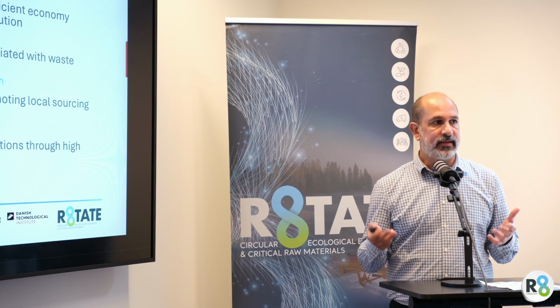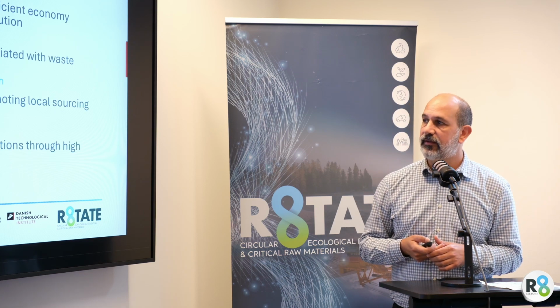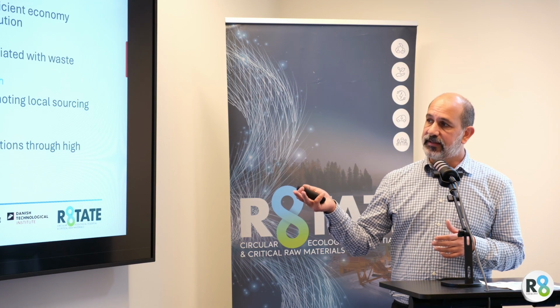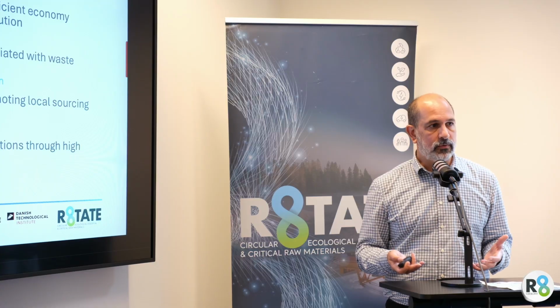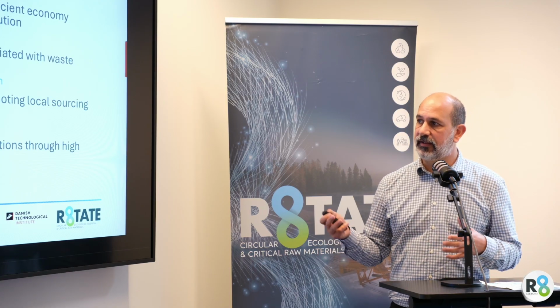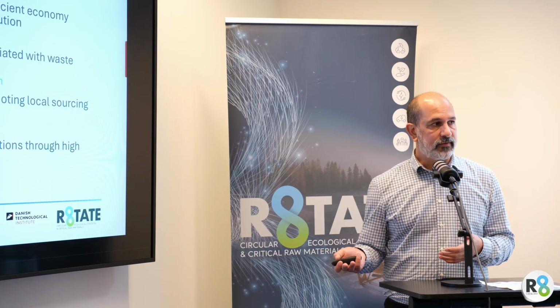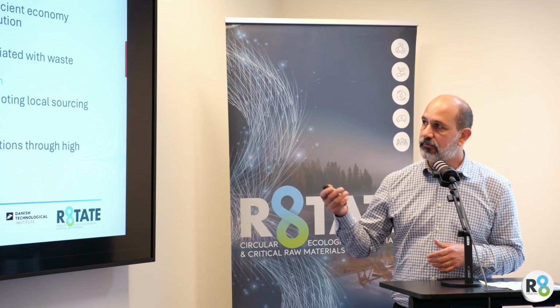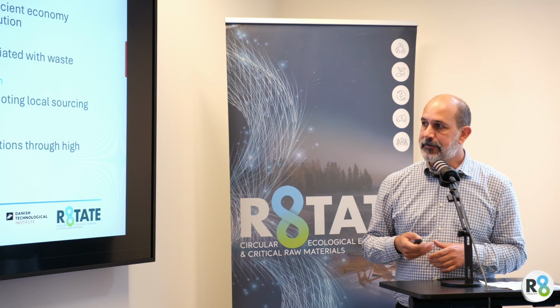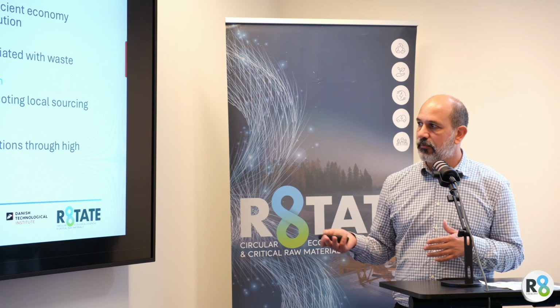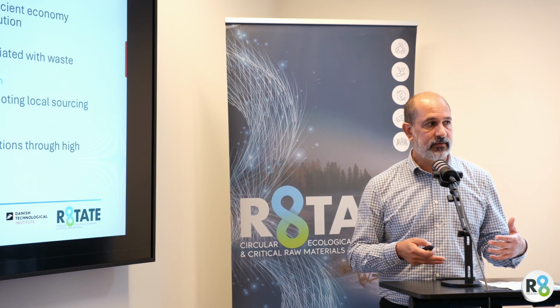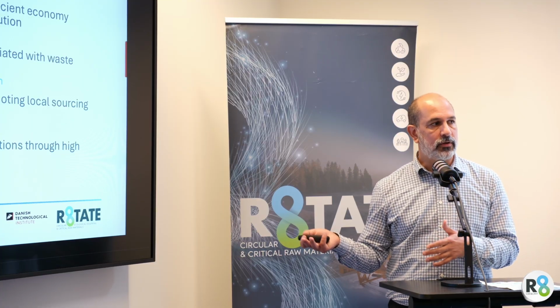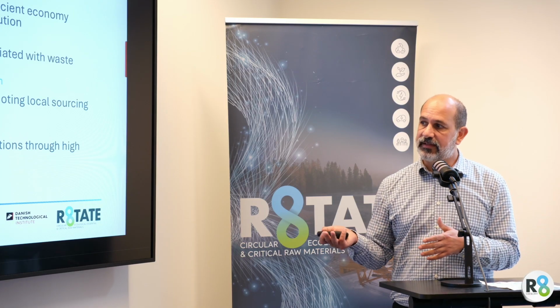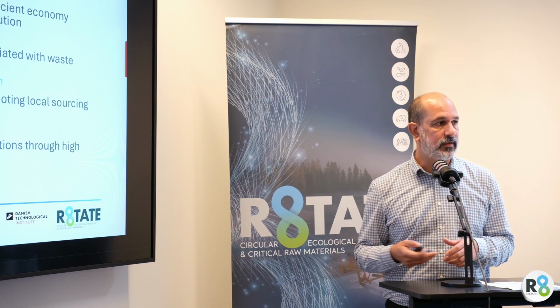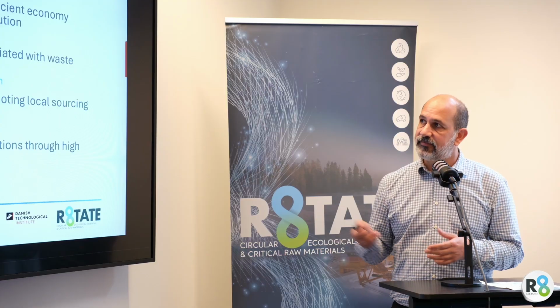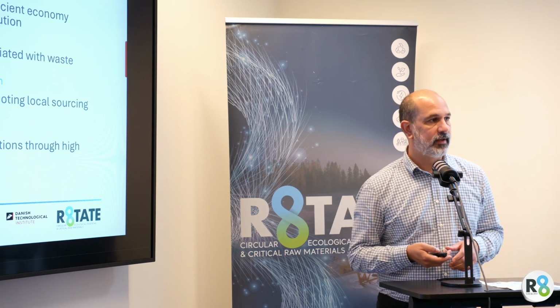And we proved with the collaboration with DTI that the material can comply with the end of waste requirements for these applications. The technologies can also enhance the resilience by using local materials and reducing the reliance on external sources. So we can produce up to 30,000 tons of material per month by using these construction materials, by using these sludges. And finally, in terms of climate neutrality and zero waste ambition, we can reach 95 to 100% of material recovery for the whole volume that Velde is processing, that at the moment is at the ratio of 70 to 80% of recovery rate. So with this, we consider that we have fulfilled our goals at the beginning of the project.